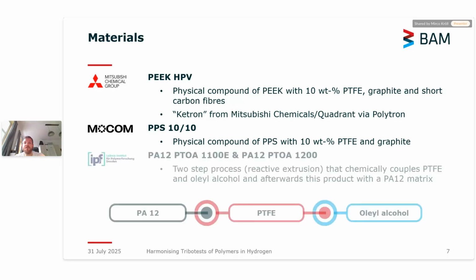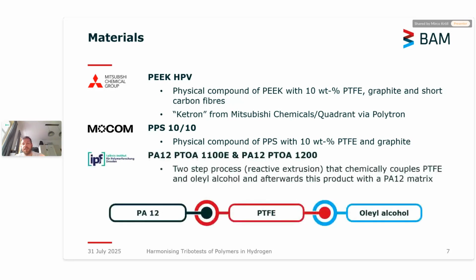The next material we used was a PPS-based material, polyphenylene sulfide, with 10% PTFE and graphite, which is not really commercially available, but similar to some existing compounds. The last one was provided by the Polymer Research Center in Dresden, which is PA12 based. The difference is that it's not a physical compound like the first two. It's actually a chemically coupled compound.